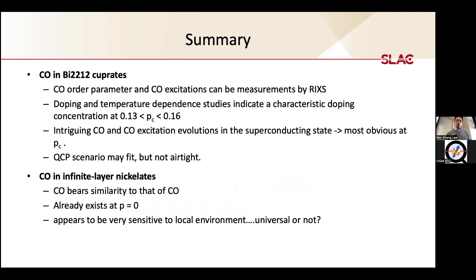In summary: I primarily focused on the charge order phenomenon in Bi2212 cuprates. Our experiments suggest there is a characteristic doping for this charge order phenomenon. Whether it's a quantum critical point is not yet airtight — some aspects fit, some don't. Better sample control and improved energy resolution below 10 meV would help resolve the picture. Thank you for your attention.